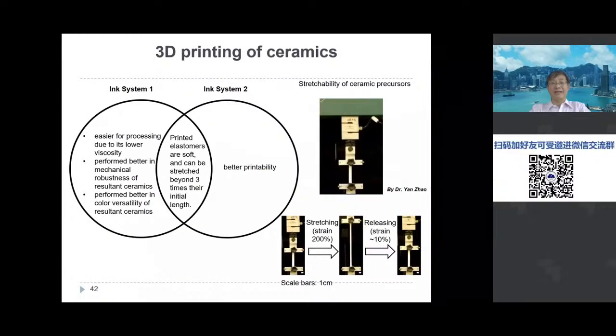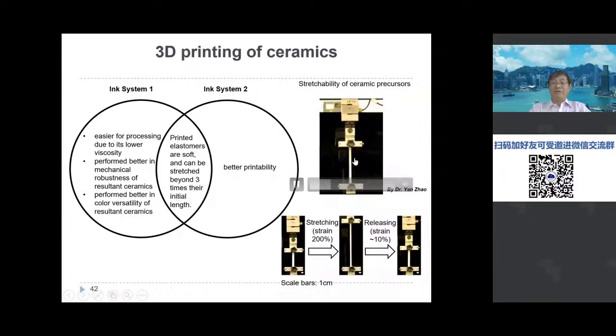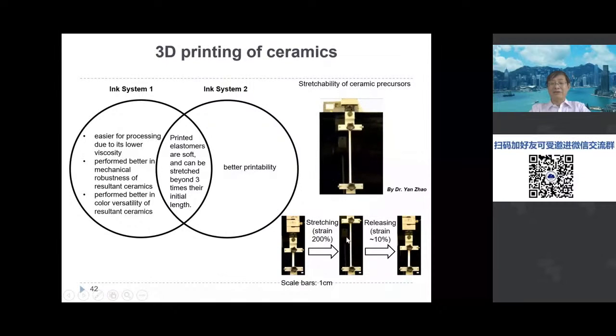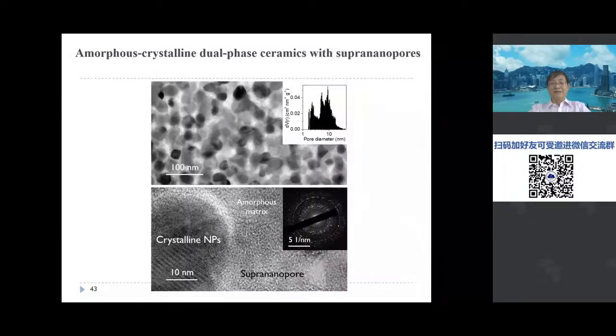I don't have time to give more detail, so the essence is here. We have successfully developed a super deformable precursor mixed with a ceramic. This can have a very high deformation capacity that allows us to produce a complex shape of the ceramics structure. After sintering, the material we obtain is a dual-phase material with nanocrystals of 20 nanometers and an amorphous matrix with silicon oxycarbide, and also a nanoscale porous structure. This structure can eventually be used as a supporting material or as a substrate for catalysis.